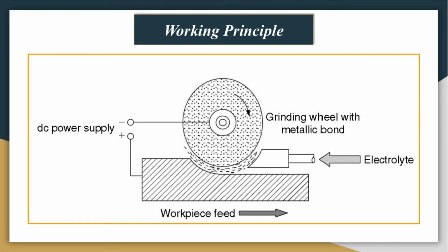The abrasive particles continuously move the machining product from the working areas. So in this machining system, the wheel is a continuously rotating cathodic tool with abrasive particles of 60 to 320 grit number on its periphery only, and electrolyte flow, that is NaNO3, we have to provide for the ECG purpose. The wheel rotates at a surface speed of 20 to 35 meters per second, while the current rate you have to maintain between 50 to 300 ampere.